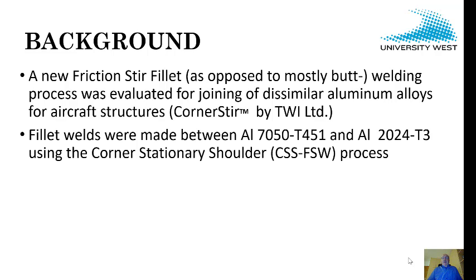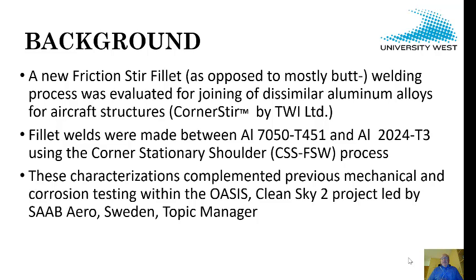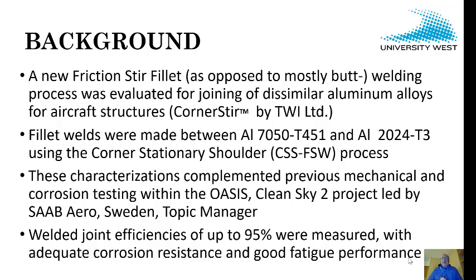A second interesting thing about this was that there are dissimilar materials: a very interesting naturally aging alloy 7050, which is aluminum, zinc, copper, and a regular duraluminum, aluminum 2024 T3 copper alloy. And that represents the skin. The 7050 represents the reinforcements in the inside of the airplane. Again, this was complementing previous mechanical tests I will show you later. But amazingly high welded joint efficiency, sometimes up to 95%, was measured. You will see that adequate corrosion resistance and good fatigue performance complemented this. So it was a very successful project.